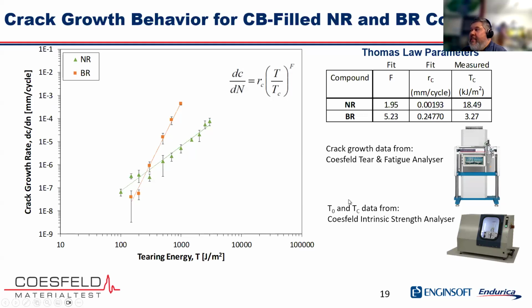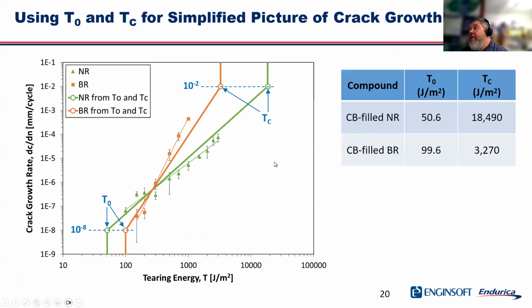This test can also give you TC, the tear strength for the rubber, right? After we do the cutting test, then we pull the blade out, and then we just do a pull to failure on the specimen, and so that can give us TC as well. One thing I want to point out is that T naught and TC, you can think of them as upper and lower bounds on these fatigue crack growth rate curves. And so as you change materials, the value of TC might change. You can imagine that the intermediate behavior is going to change similarly.